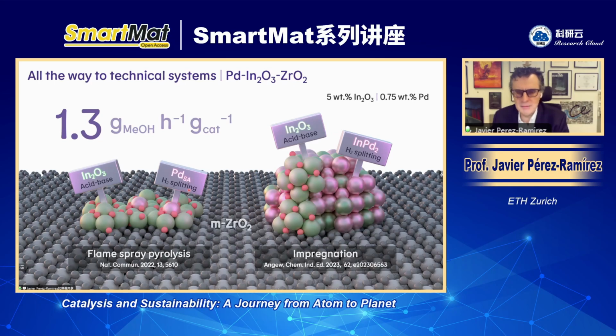Now, what is very important in these architectures to deliver the function of producing methanol in a very efficient manner is that you need to combine acid-base function, which is delivered by the indium oxide, with the ability of doing the redox chemistry, which is the hydrogen splitting. And this is done by either palladium single atoms in this architecture that are stabilized on the surface of indium oxide, or it can also be done by indium-palladium alloys, which can be produced by impregnation, as long as the acid-base function, which is indium oxide, and the hydrogen splitting function are integrated close together in the catalytic material. So that shows you how important is the nanostructure of the material. Without atomic control, solving planetary problems is quite difficult.